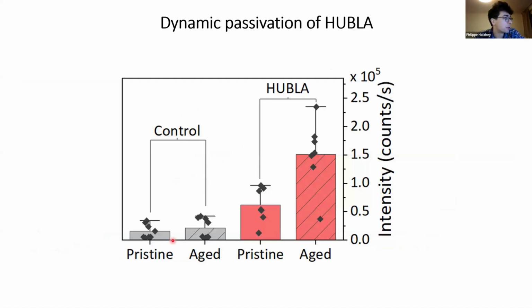Here we have some statistics. So here you see the pristine and then the photoluminescence intensity after the aging. So there's a very small improvement. But the pristine films have a lot higher luminescence from the beginning and then even improve significantly more with the aging.